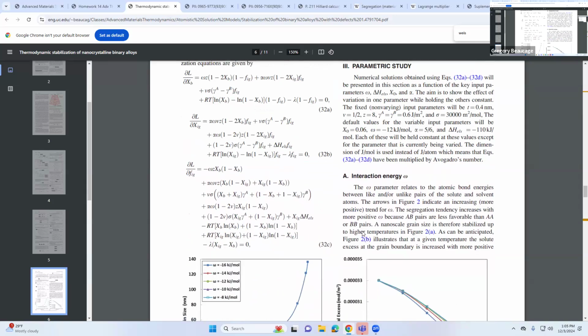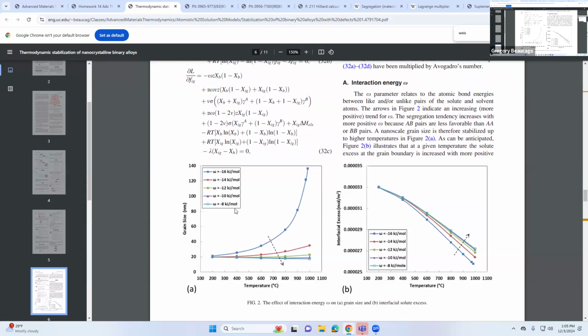So parametric study means he's going to look at what happens if I change these things to get different behavior. He's trying to get the smallest grain size he can at high temperatures. You're going to ball mill the two metals together. Then you're going to heat it up and anneal it at some high temperature. And typically the grains would grow. They would just keep growing to some large size. When you want to prevent that, you want to keep them at a small size. He's got a 20 nanometer grain. He wants to have it stay at 20 nanometer all the way through at highest temperature. So he mills it down here, then anneals it up here, and then quenches it. The kinetics are kind of gone from this equilibrium.